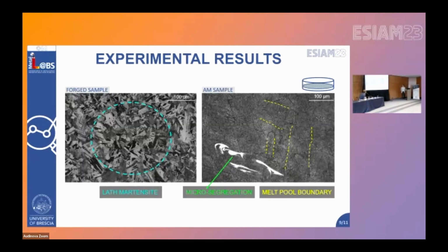We are still not sure, because the problem is that this microsegregation, we found them both at the melt pool boundaries and inside the melt pool. So we cannot say for sure that the cavitation erosion nucleates at this microsegregation point, or is just general over the melt pool boundary. We need further studies to be sure of that. For sure, the fact that austenite is way softer than the martensite makes us think that probably this should be the weaker point, but still we cannot say for sure.